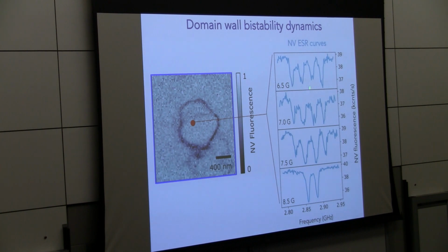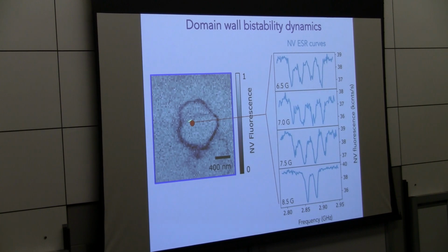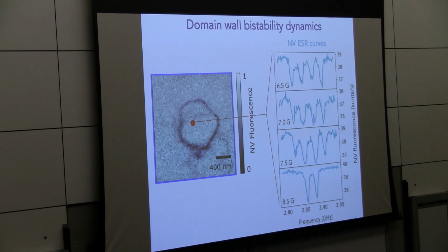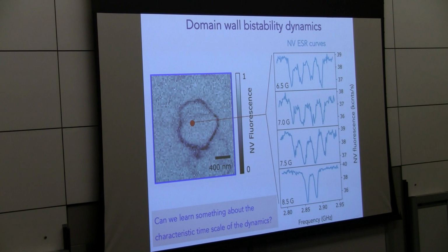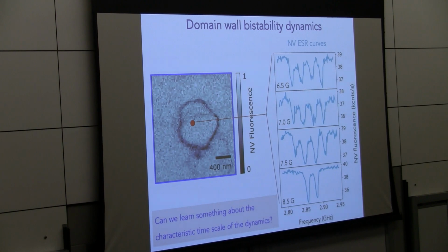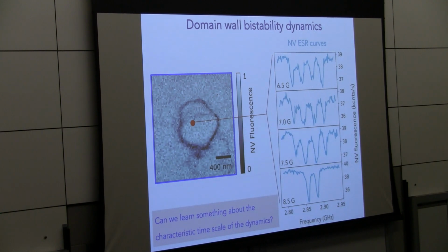And as we increase the magnetic field, it's not shown here, but the domain wall settles on the smaller diameter position. Okay, so we know that it's jumping. Can we say something about the time scale? In this case, we could not see the hopping happening in real time, so we have a lower bound on the time scale of the dynamics. But can we say something about the faster dynamics, how fast it could possibly be?